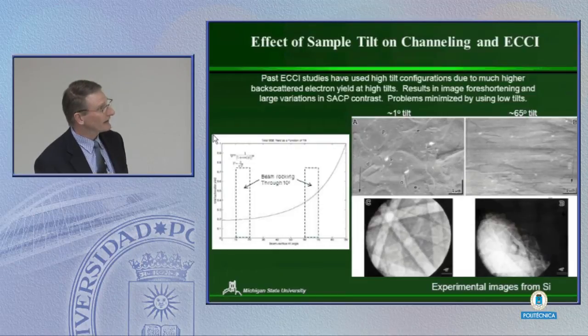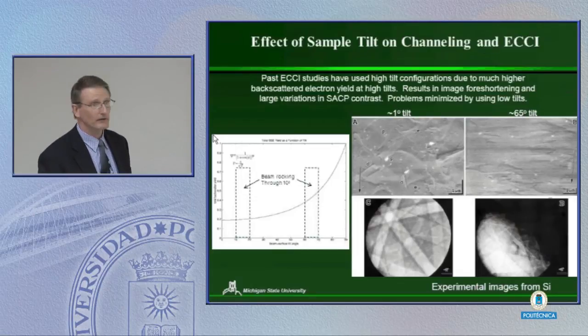And so your selected area channeling patterns will come out something like this. But if you do that same sort of beam rocking to, say, 10 degrees here, we can see that we get much more even intensity, and this just makes life easier.